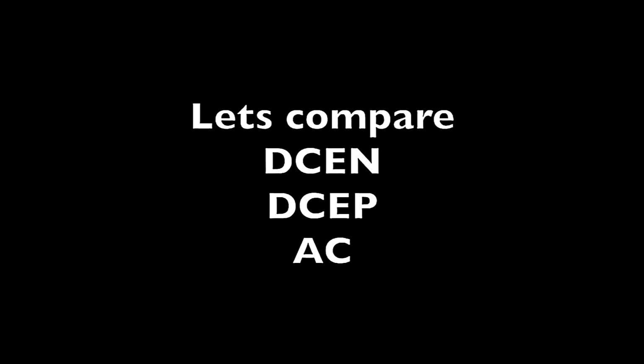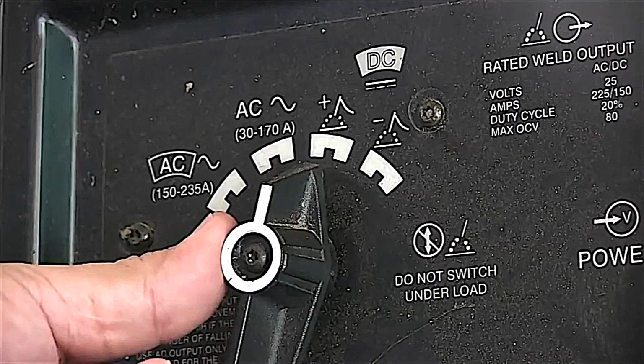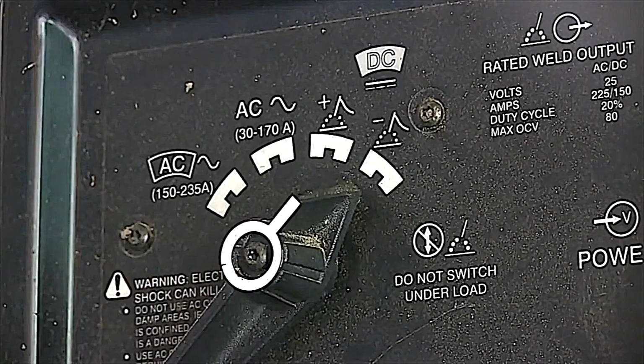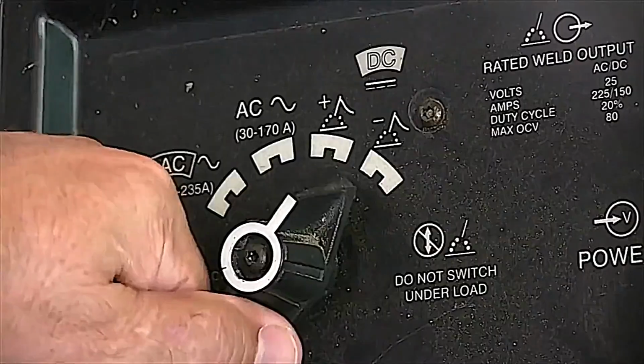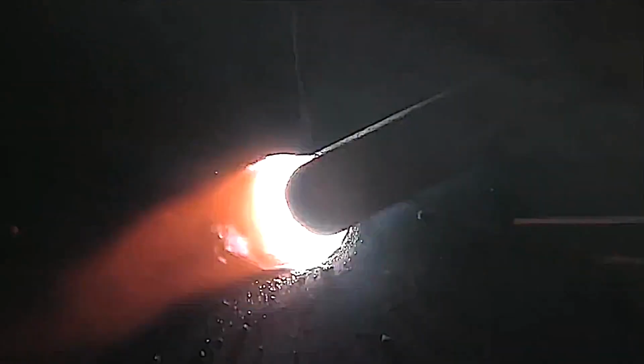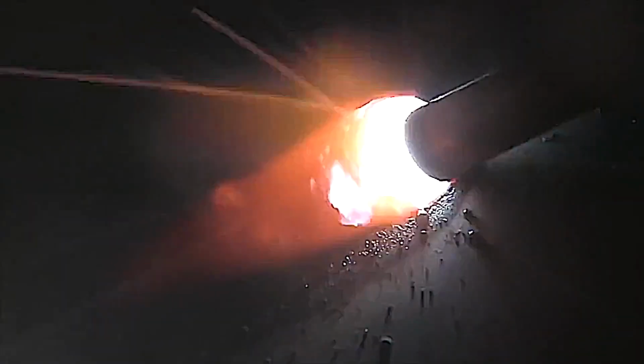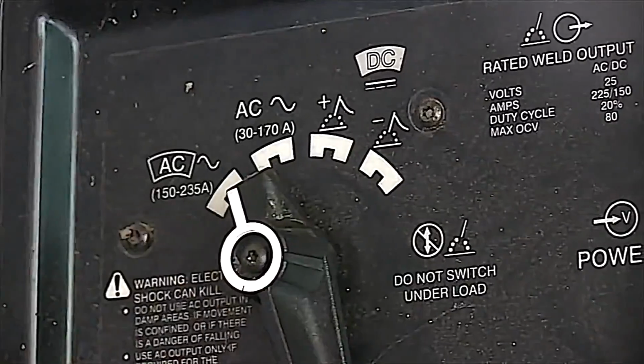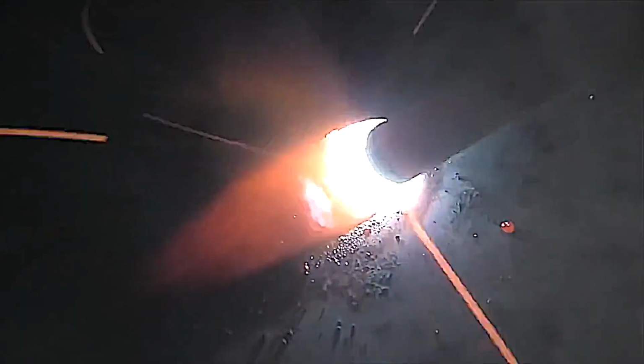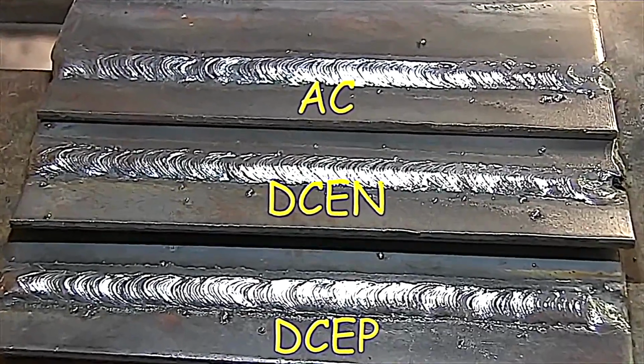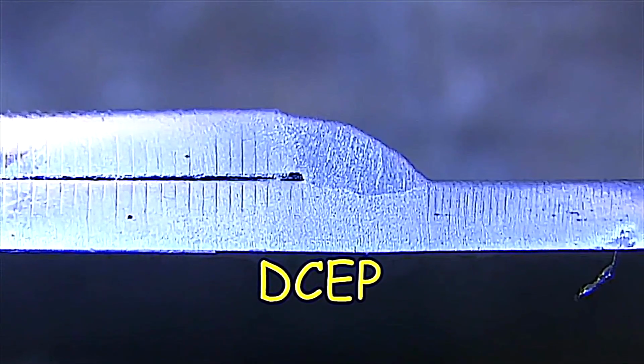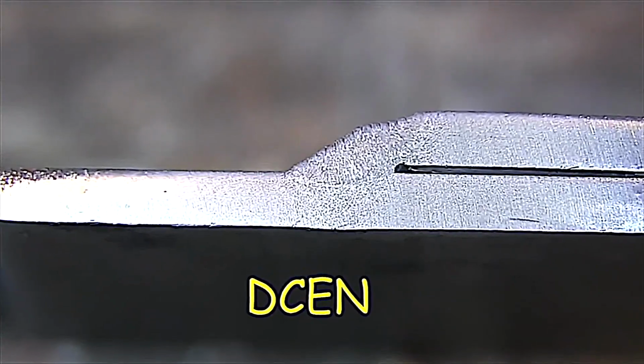So will a 6013. An awful lot of 6013s are used on AC buzz boxes. In fact, I did a video a while back. I compared DCEN to DCEP to AC. 3 different welds, cut and etched all of them. The puddle actually looked almost identical on all 3 welds. Very subtle differences, no matter if I was on DCEN, DCEP, or alternating current, just maybe a little bit more spatter on alternating current, but cut and etch test and the visual all looked very similar. Not much difference at all.